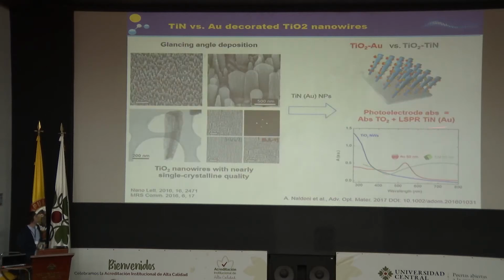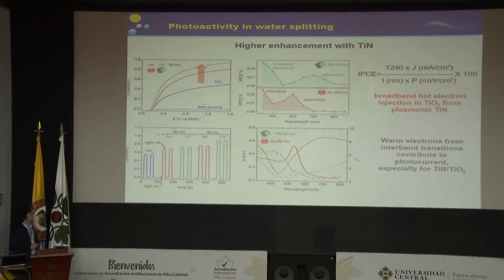So what we did, we developed titanium oxide nanowire electrodes, where we deposit gold particles or titanium nitride particles. And as you can see here, the absorption of the particles deposited on top of the electrode increased the absorption at longer wavelength with respect to the band gap of titanium oxide. And then we measured, of course, the efficiency of our materials in a photoelectrochemical cell. Here is the JV curve of pristine titanium oxide. And here is the curve of the electrode where we deposit the same amount of gold or titanium nitride. You can see that we got a doubling of the current from the pristine material to the titanium nitride titanium oxide composite, but also that titanium nitride outperformed gold by 25%, which was really not bad.